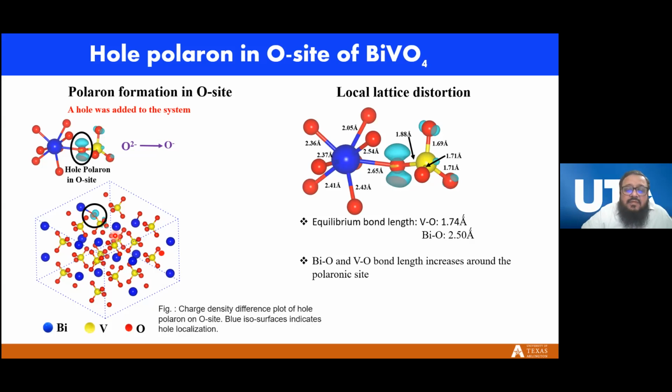For photovoltaic water splitting, either by photochemical or photocatalytic means, the ratio of the effective mass of hole to the effective mass of electron plays a good role in reducing the recombination rate of electron and hole, right? So far it is believed, from the theory of Zhang et al., who published a paper in 2012, that this is the established theory. They say that the effective mass of the hole should be much larger than the effective mass of the electron. But is it not also true the other way?